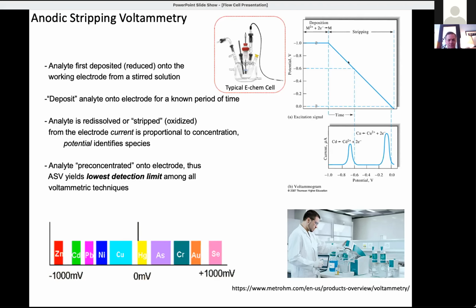And so what I have here in the diagram is at first the excitation potential, which strips the ions out of solution, and a sweep of voltage from a negative voltage to the reference voltage, which shows the stripping of the metal being oxidized off of the analysis electrode back into solution, showing the detection of cadmium here and the detection of copper. And if you integrate the area underneath these peaks, this gives you the ability to quantify the amount of material which was deposited on the electrodes.